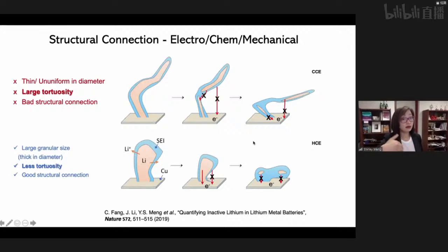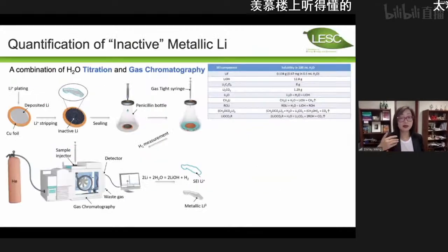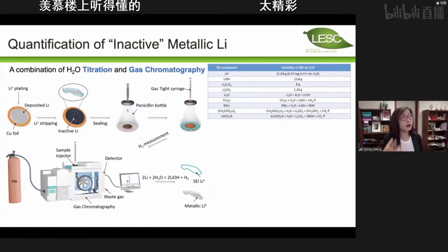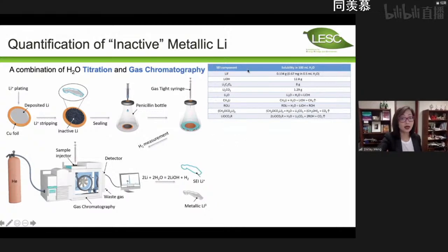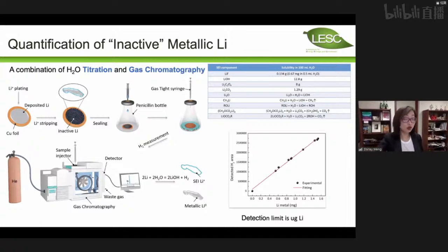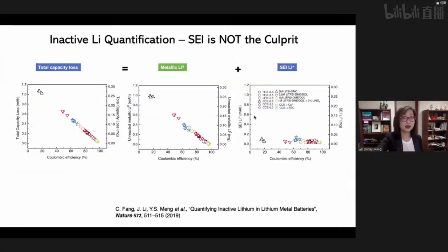So that's the reason in our Nature paper we hypothesize that the SEI is not the major culprit for low efficiency lithium metal batteries, but the microstructure control is. And to emphasize this important discovery, we also complemented the TEM data with this new titration gas chromatography measurement. The principle is quite straightforward, because of all the SEI components, lithium metal is the one that will give you hydrogen. So we only need to measure the hydrogen amount. When we measured it, we found a very interesting phenomenon that agrees with our hypothesis: all the capacity loss is perfectly correlated with the metallic part of the lithium, not with the SEI.